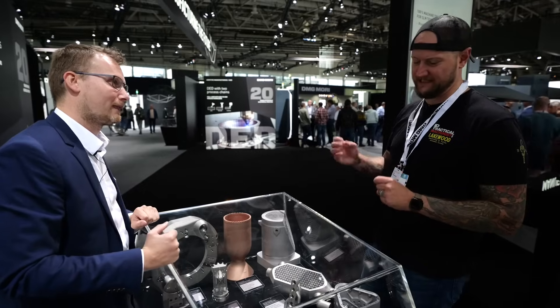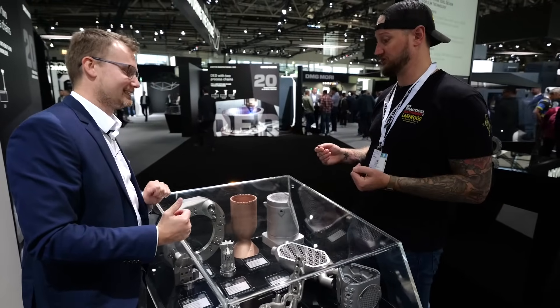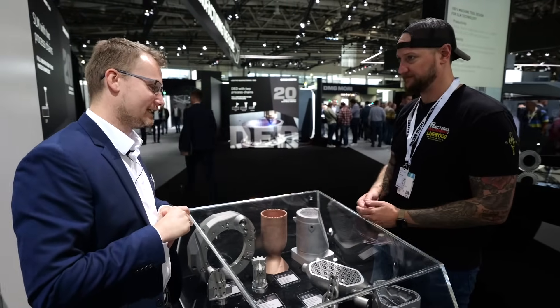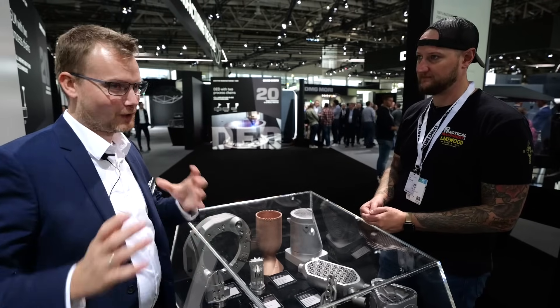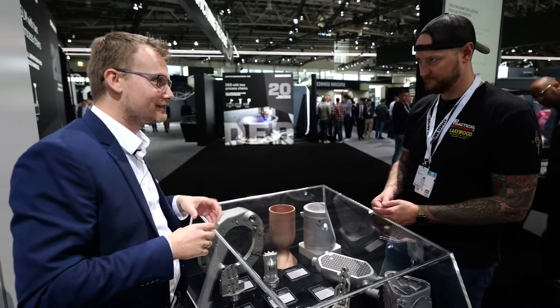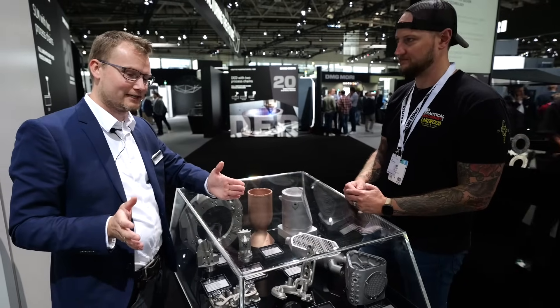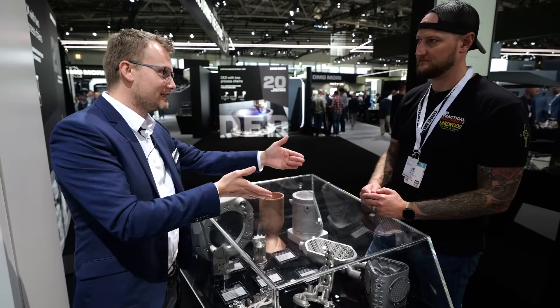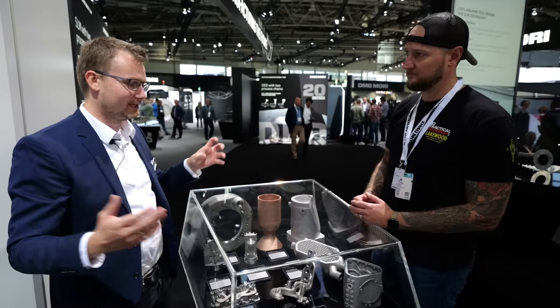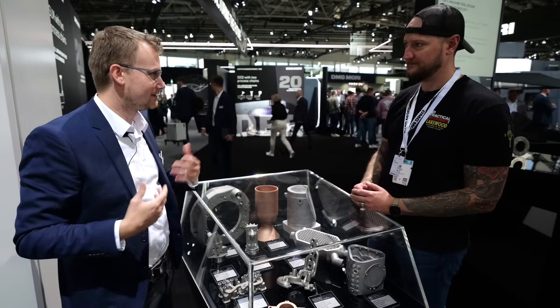I remember we were looking at the LaserTech DED — you guys were doing an additive process going into a draw bar for DMG Mori machines. So not only are these things you can't do otherwise, you're testing the process and the final application all in your own facilities. Printing is one part. To reduce residual stresses we typically have a furnace afterwards. Then we take the workpieces on the base plate, shift them after the furnace to the machining center, machine the upper side off, and cut parts off by bandsaw or wire EDM before bringing them back to the machining center for the finish.